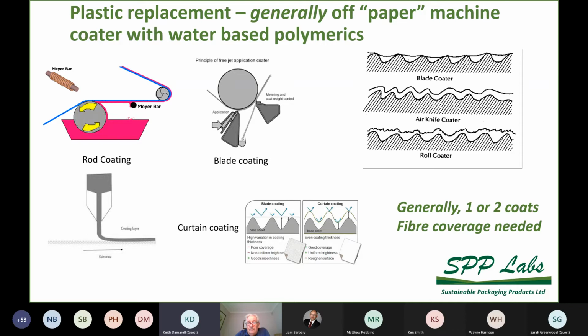If you look at the top right-hand diagram, you see the effect of a blade coater. The metering essentially just meters off the coating, and you get thicker and thinner layers over the peaks and troughs of the paper. As a consequence, most off-machine coating operations apply more than one coating. They usually have 2 coating heads. The first coating head is then covered up by the second coating head, and that avoids things like pinholes in the coating. Other coating methods can include curtain coating.